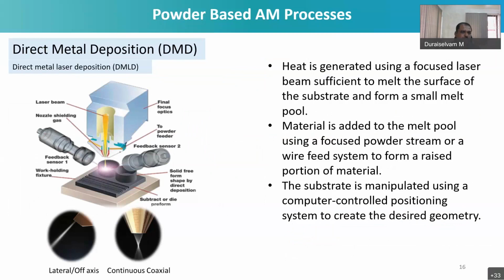And direct metal deposition, it is more of laser cladding, right? And if you have a coaxial powder feeding nozzle like this, whether it is a lateral or off-axis system or a continuous coaxial system, where you have some kind of a powder feeding mechanism where the powder is fed into the coaxial nozzle of the laser, and the laser light will come from the middle, and then it melts the material which is meeting the already prepared layer, and then it will get deposited.